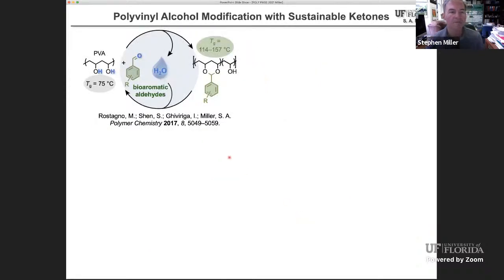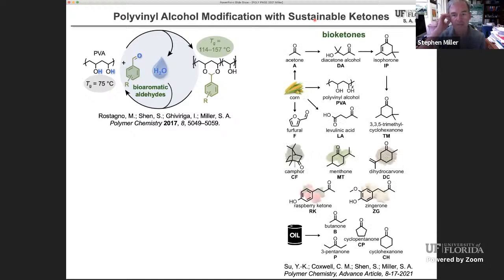So subsequent to attaching these bioaromatics, which are somewhat available but somewhat expensive, we wanted to try to attach a variety of ketones, making polyketals from polyvinyl alcohol. And so we attached many of these. Not all of them would attach. For example, camphor and menthone are essentially too bulky, we think, to attach to any substantial degree to polyvinyl alcohol, but most of the others will attach.